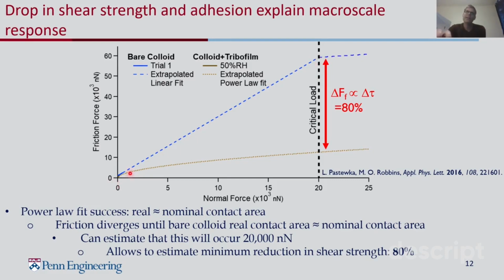And so by extrapolating these curves to this critical load, and we could calculate this critical load because this paper gives roughness parameters to do so, and we know the roughness parameters from measuring the bare colloid case, we could show that this critical load was about 20 micronewtons.